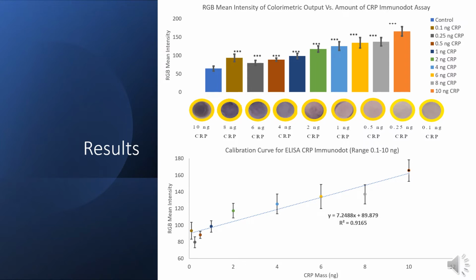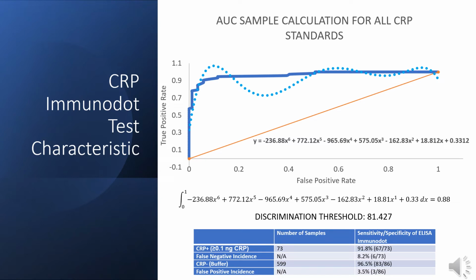setting for quantitative screening. To determine the colorimetric output cutoff for false positive and false negative tests, and to determine the quality of the plot versus the control, specifically if a certain CRP standard should be used in the calibration curve, a receiver operator characteristic curve was generated to detect the diagnostic ability of the ELISA immunodot in response to a changing discrimination threshold. The receiver operator characteristic curve derived from combining all CRP standards had an area under the curve of 0.88, indicating a borderline outstanding test.